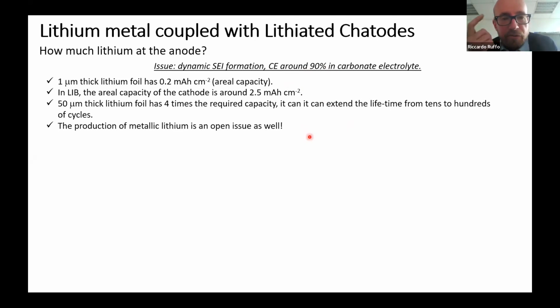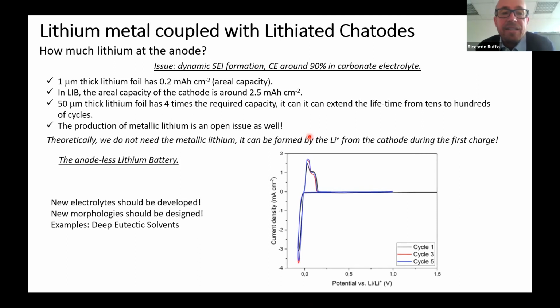But if you have a cathode where the lithium is provided during the first charge, you don't need the lithium at all at your anode. This is the concept called the anode-less lithium-ion batteries, where the metallic lithium anode is formed during the first charge with the lithium ions coming from the cathode. For these applications, new electrolytes should be developed because the current carbonates cannot be used for that. New morphologies in terms of anodes should also be